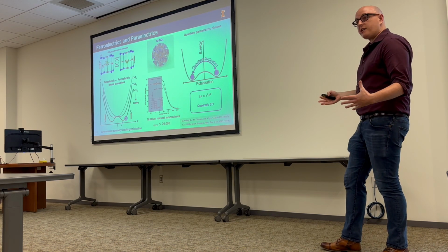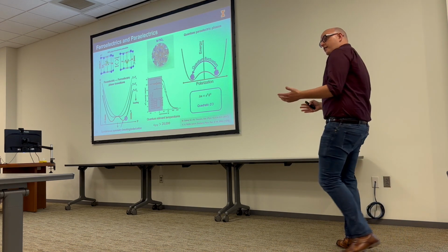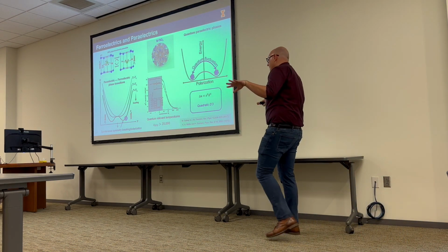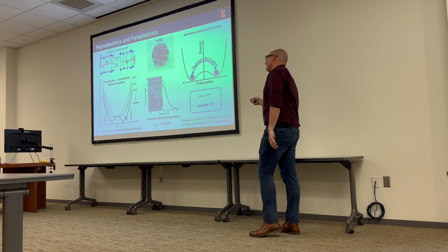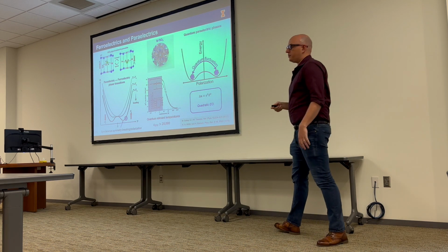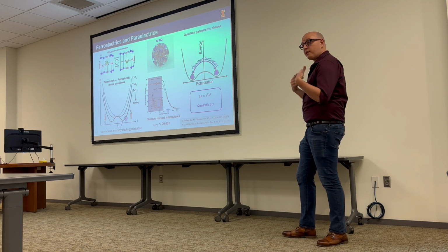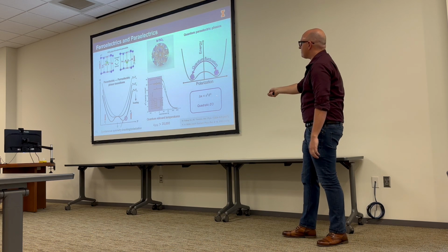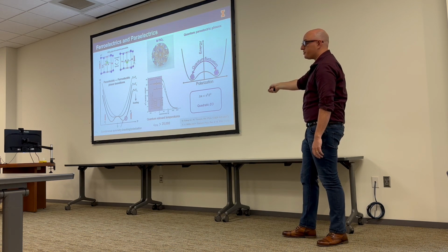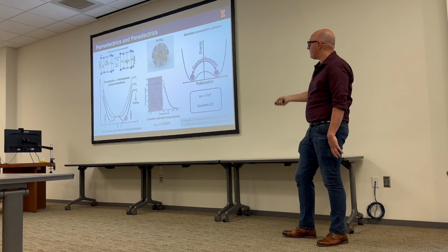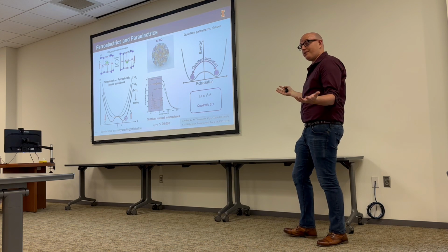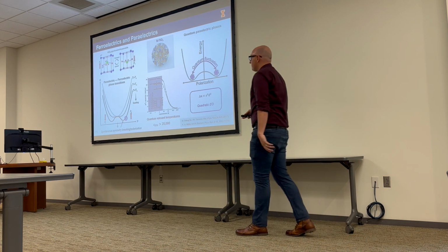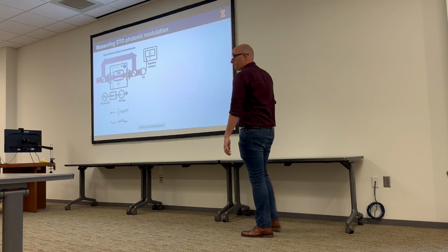And that's actually great, because that means the dielectric constant is always high, and it's consistent over our entire temperature range. In this case, that also means that our system never undergoes this phase transition, it never becomes polar. So our response to DC bias is only ever quadratic. But since we get this quadratic response with electric field squared, but also dielectric constant squared, if the dielectric constant's big, we don't really care. But it does mean that we have to bias this crystal to make it nonlinear.